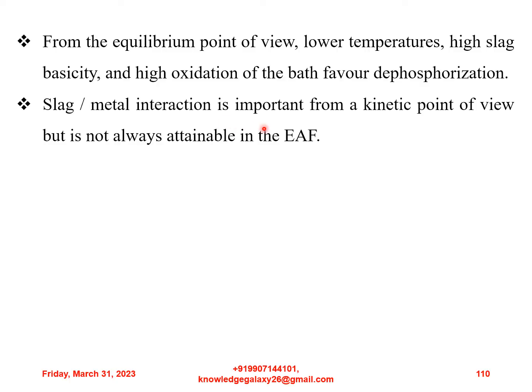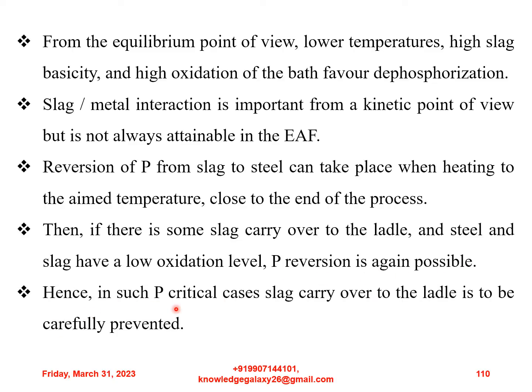Slag and metal interaction is important from a kinetic point of view, but it is not always attainable in the electric arc furnace. Reversion of phosphorus from slag to steel can take place when heating to the aimed temperature close to the end of the process. Then, if there is some slag carryover to the ladle and steel and slag have a low oxidation level, phosphorus reversion is again possible. Hence, in such phosphorus critical cases, slag carryover to the ladle is to be carefully prevented.